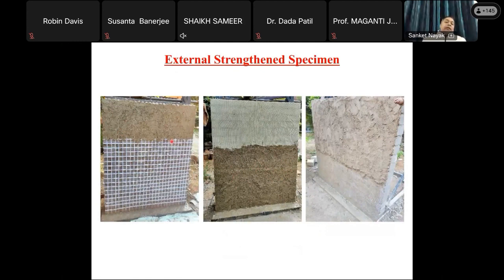And this is the on-site picture. Whenever we have casted the walls in the laboratory, you see this is the PP band cage, and then the plaster is provided. This cage or the grid has been optimized after a number of testings. We have gone for the basic tests like the bond test. In fact, Dr. Susanta has carried out all these testings, and he has optimized this. So the in-plane, out-of-plane, the bond behavior, all the things. And then here it is for the geonet, and it is for the steel wire mesh.